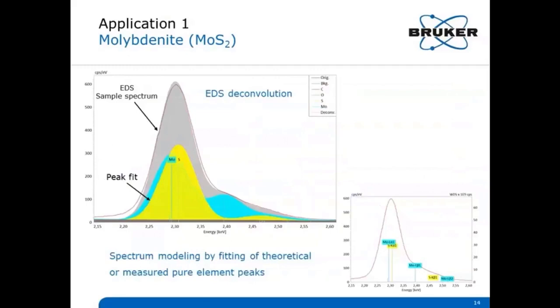However, EDS has a great tool, which is called peak deconvolution. The actual measured spectrum is modeled by fitting the peaks with pure elements. There are several models available based on theoretical or measured profiles, single line or line series fits, and different fitting algorithms. Peak deconvolution can solve overlap issues in most cases. On the upper left side, you see fitting of these molybdenum and sulfur overlaps.